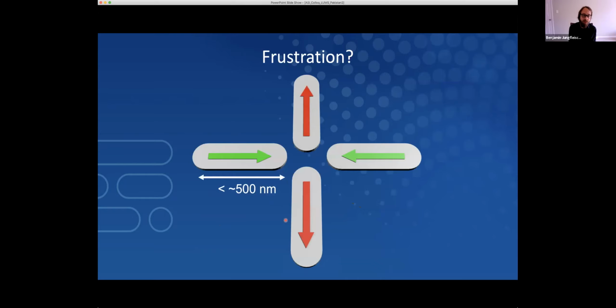Now, we are typically making devices with elongated elements like these, with a length smaller than 500 nanometers and a width smaller than 100 nanometers. And we choose the thickness so as to achieve a single domain state. So typically, the thickness is between 15 and 20 nanometers.